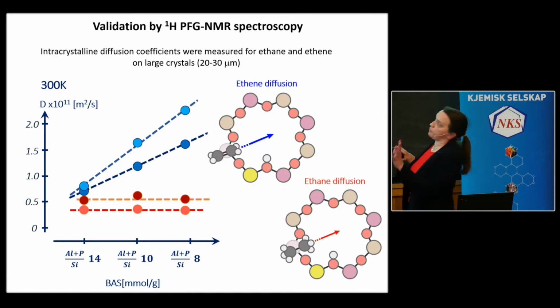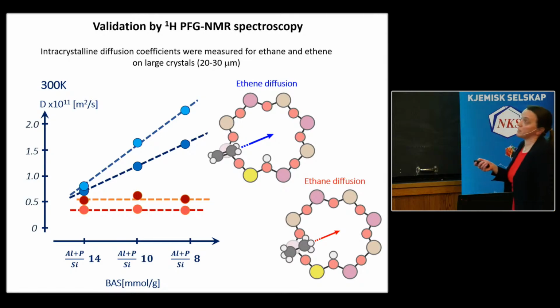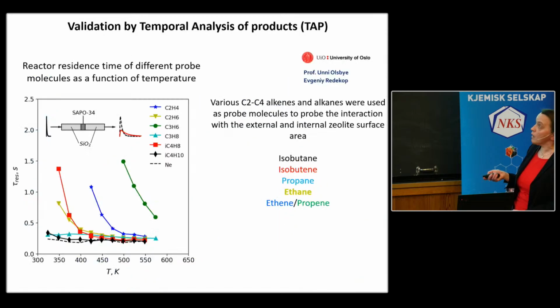So I'm not going to explain too much of the experimental details, but for example, here you can see the diffusion coefficient in terms of the acid site density. And this is for ethane, so no double bonds. For this ethane, we can see that there is no influence of the acid site density. If you have this ethene, then we can clearly see that the diffusion coefficient indeed enhances by having a higher acid site density, let's say, by having Brønsted acidic protons. So this confirms basically what we indeed also saw.